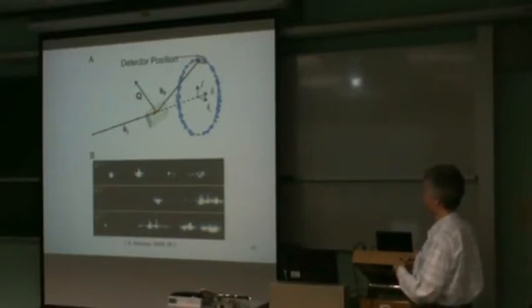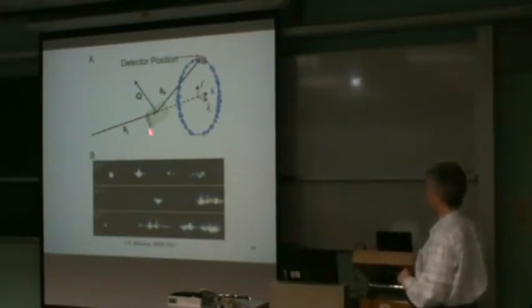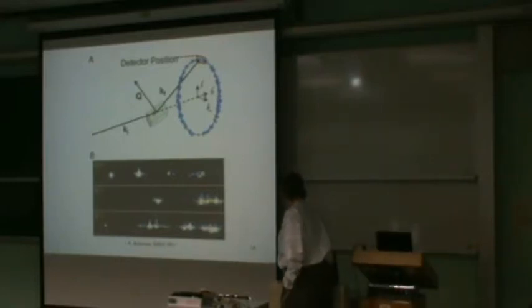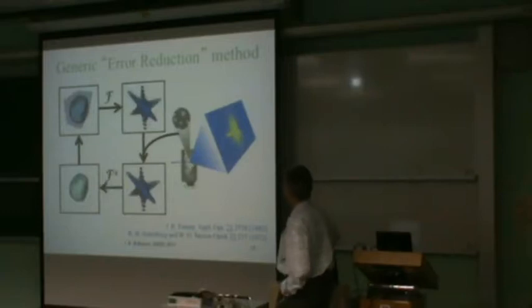When you do this for semiconductor devices, they're usually with a single orientation on a substrate, so you have to space them apart enough that you can shine the beam onto just one of them. So the focusing is particularly important, so that you can zoom in on just a single device that you would like to look at. But the method is exactly the same. You get one Bragg peak, and you would just measure that one Bragg peak, and then you can look at many devices in a lithographed sample if you wish, and they would all have the same orientation, so you wouldn't get the powdering for those, but you can still do the experiment.